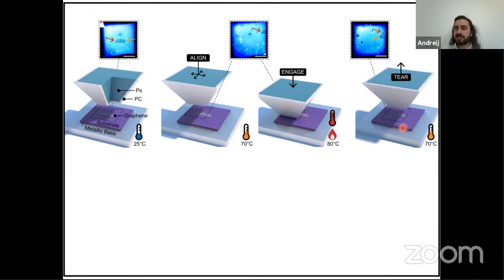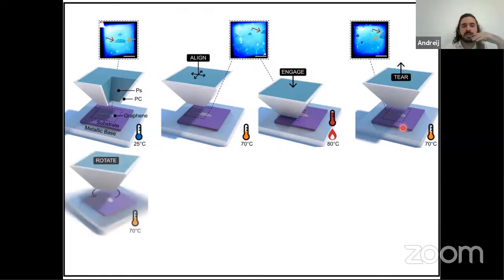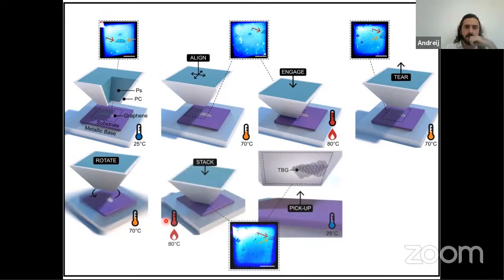We now have two graphene sheets which were also once one single sheet. So they are perfectly aligned, and we just need to rotate the base, and we can stack these two sheets, and we can form our TBG. So we stack them and pick the two pieces, which are here located at the pyramid stamps, and we have the TBG formed. Okay, so this is an optical image.